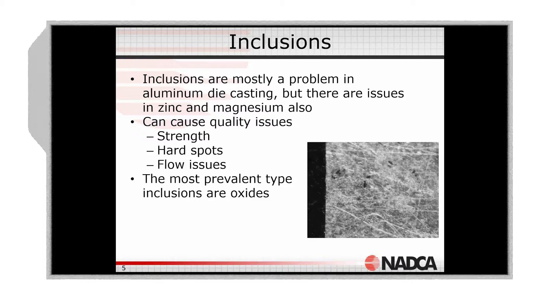Inclusions are potentially going to upset your flow. If you get large inclusions — large pieces of material — they can actually come through the gate or combine in the casting and obstruct the flow. You also have porosity concerns or other flow issues due to inclusions in the metal. The most prevalent inclusion is going to be the oxides in the metal.